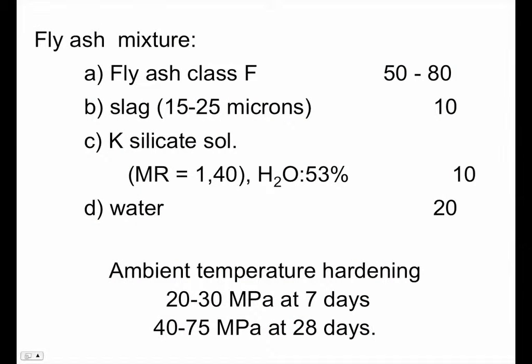We have super thixotropic mixtures, that no longer move, and as soon as they are in rotation, they are super fluid. So it is a behavior that one has to be accustomed to. So fly ash 50 to 80 parts, 10% slag. So when I'm telling you that the slag is a chemical, this is the proof here. We only add the slag so that it starts the alkalination and degrades and depolymerizes in order to enter into the system.